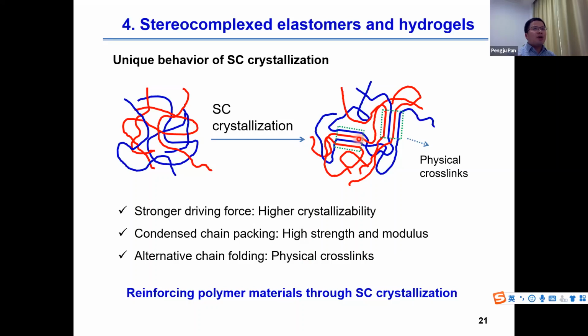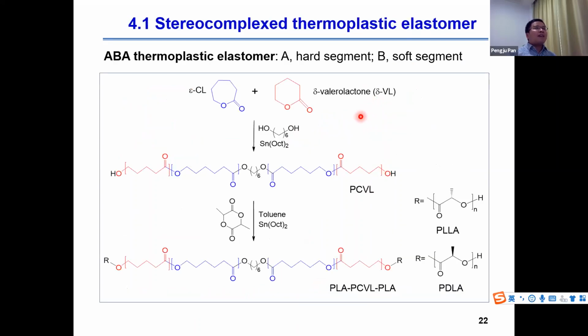We use the stereocomplex crystallization to reinforce elastomer and hydrogel. In the first case, we use the stereocomplex crystallization to reinforce the ABA triblock polymer. A is the hard block, either PLA or PDLA. B is a soft mid block. We use a random copolymer of caprolactone and valerolactone. We also mix the PLA triblock and the PDLA triblock polymer to prepare the stereocomplex elastomer.